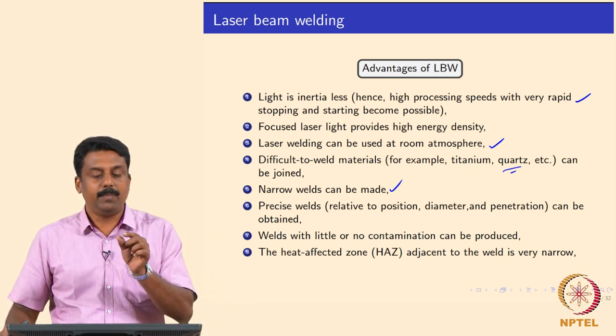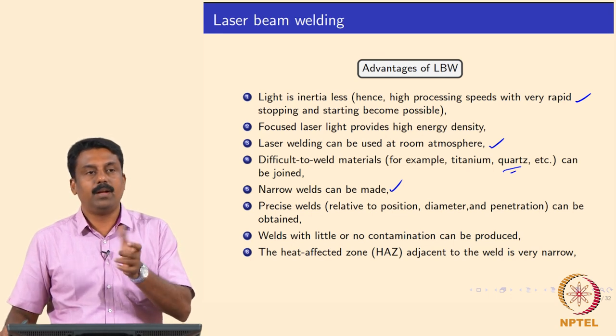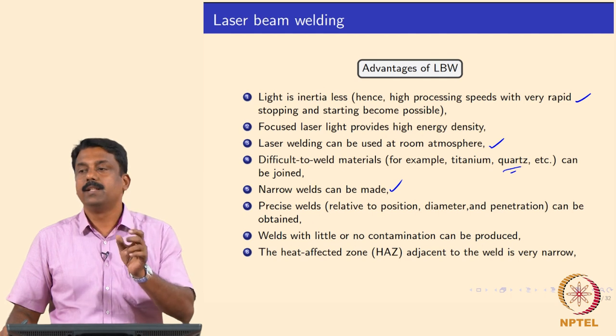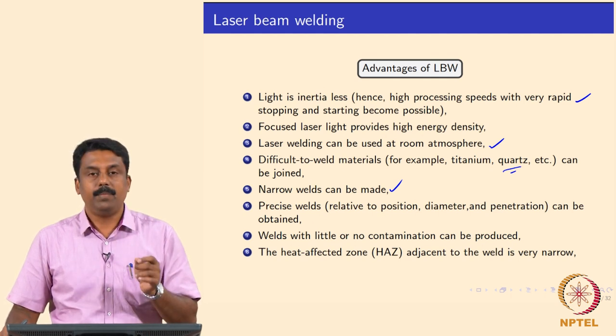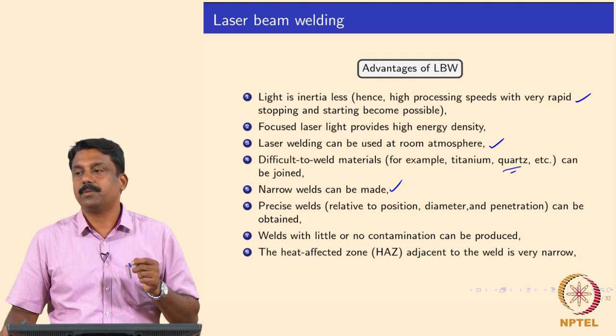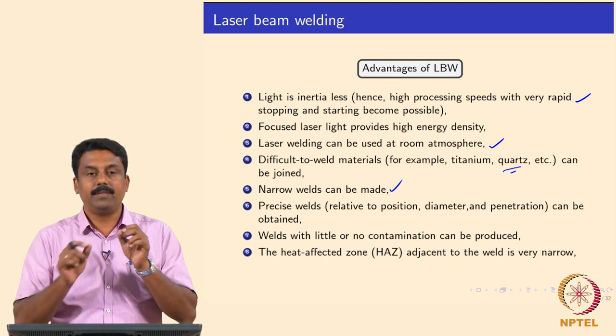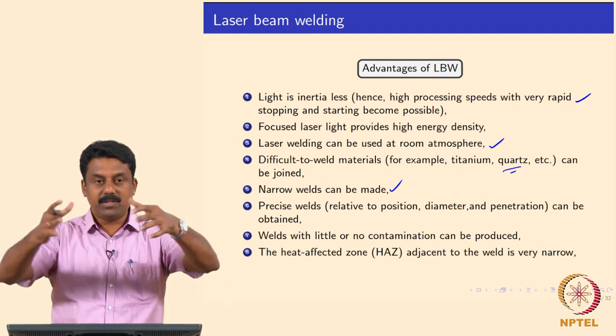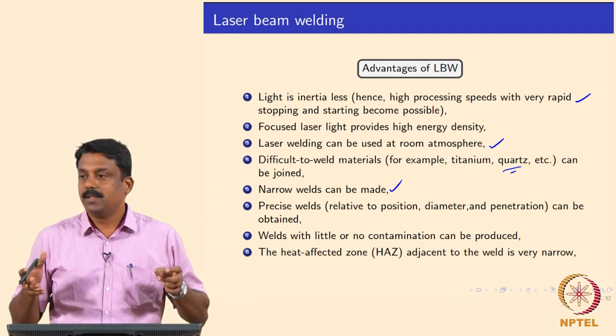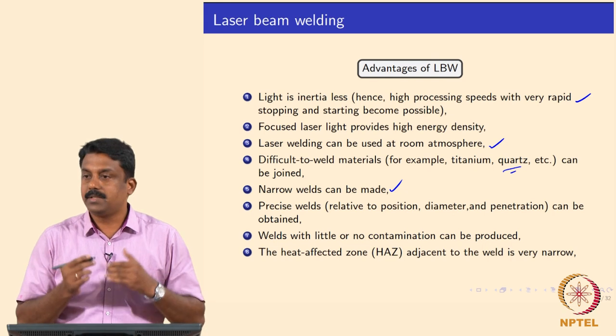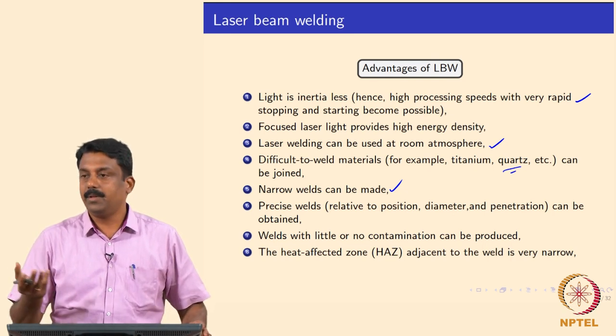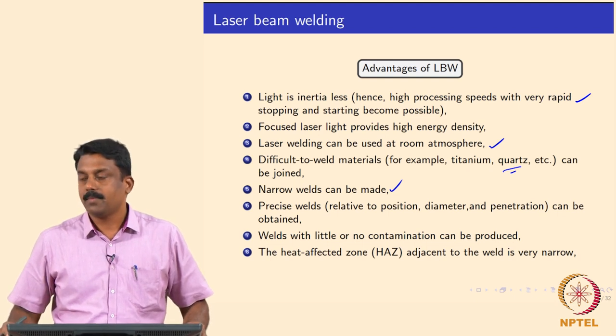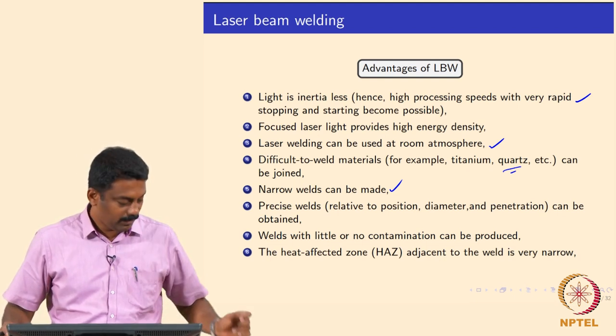The weld has very little contamination because you can also have shielding. Because of the very confined heating, the heat affected zone is also very narrow and you will have a very steep temperature gradient. The keyhole can be hardly 1 or 2 mm if you are using a beam size of 50 microns. You will end up forming a keyhole of 1 mm and a weld pool of 2 or 3 mm size. So very fine seams can be made. Because of the confined heating, heat is also extracted rapidly because you have much more surrounding mass, so the temperature gradient will be very steep and the heat affected zone is also very small.